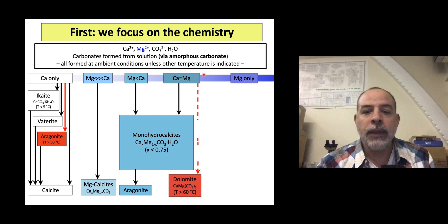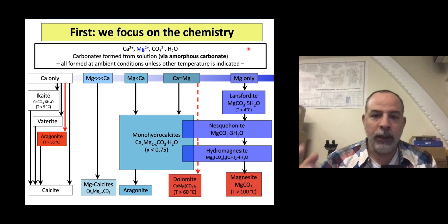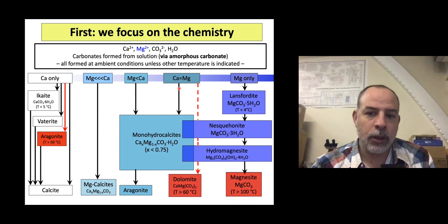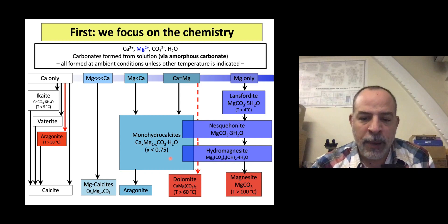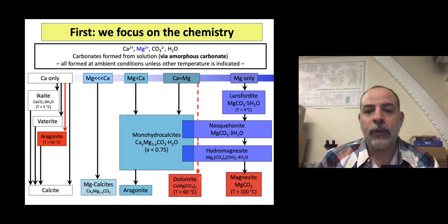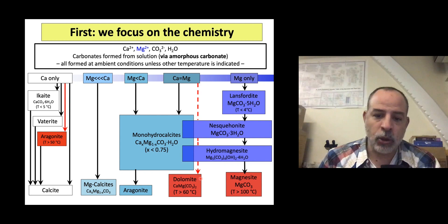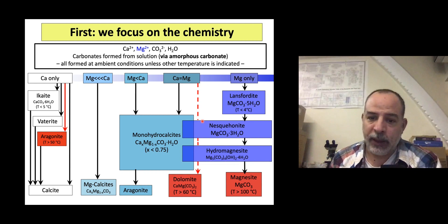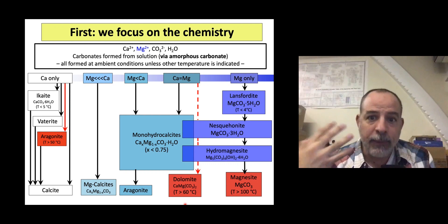When we have only magnesium, we produce magnesium carbonates. The problem when targeting calcium equal to magnesium to produce dolomite is that this red line is very thin. If we go slightly to the left or right, we may produce dolomite that also contains other minerals — magnesium carbonates. Our end product might be 99% dolomite and 1% hydromagnesite or nesquehonite. So we don't have a pure phase, and finding that thin line can be complicated when you are starting from scratch.